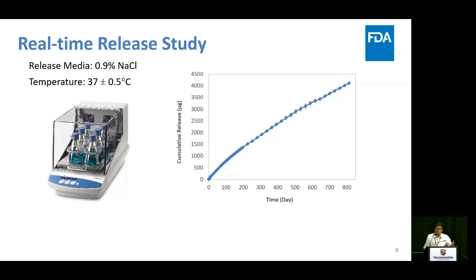Now, how long does it take for the drug to saturate the membrane? To answer this question, we did several short-term release studies. For these studies, we did a release study in real-time conditions for 5 hours and then kept the device in storage for a specific period of time. These times were 1 day, 2 days, 4 days, 1 week, 2 weeks, and a month. And then we tried to model fit the release data. When we plotted the release rate constant against storage time, we saw that after 4 days, the release rate constant plateaued. So from here, we can conclude that the time it takes for the drug to saturate the membrane is around 4 days.